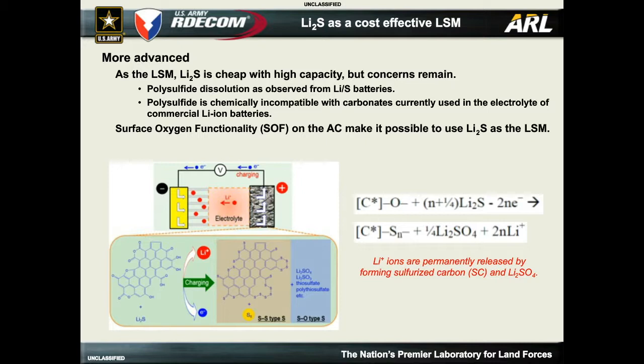And then when you charge up the cell initially, you decompose the lithium sulfide, form some lithium sulfate and lithium metal. The sulfur bonds to the activated carbon and essentially becomes inactive, replacing some of the oxygen functionality that's on the activated carbon. Most activated carbons have a large content of oxygen in them, somewhere around 5 to 10%. So this approach works pretty well.